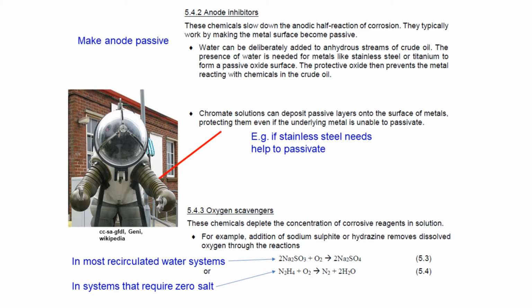And the metal will break down. In this situation, we can talk about an anode inhibitor: deliberately adding water to what would otherwise be an anhydrous stream of crude oil. The presence of water then provides the ability of metals like titanium, and this also applies to stainless steels in some situations, to reform their passive oxide surface. In this case, I've provided anode inhibition - I've slowed down the rate of corrosion by making sure the metal is behaving in the passive way that you expect it to behave.